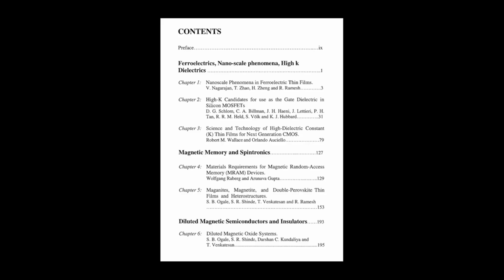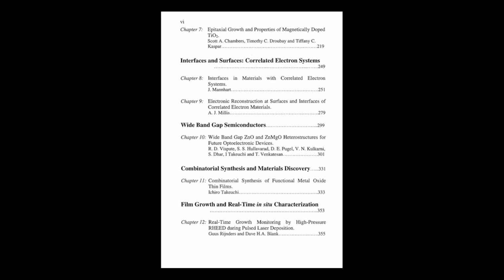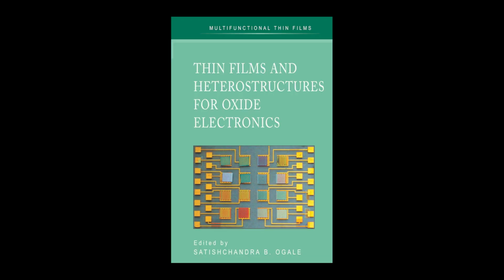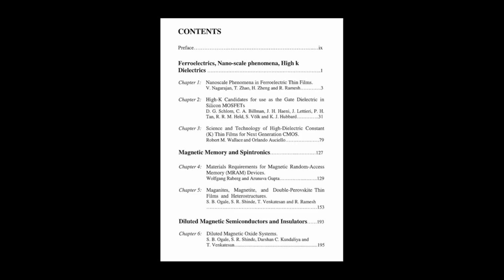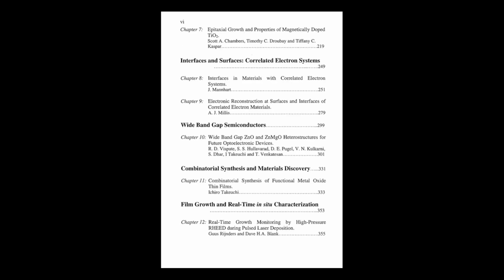So that rapid alternation forces the barium, strontium, titanium, and oxygen atoms to mix together really well at each point, forming a continuous alloy gradient. Yes, it creates a pseudo-binary composition spread. And then comes the fast characterization part. For that BaxSr1-xTiO3 example, they used a scanning microwave microscope. To measure what? To measure the dielectric constant point by point across the entire chip, mapping K as a function of the composition x. And they found the sweet spot.